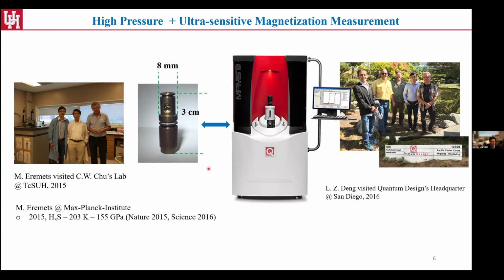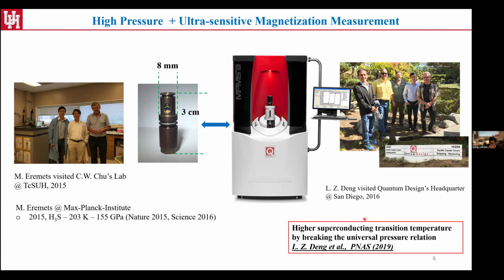With that experience, I got into doing magnetization measurements under high pressure. One of the key challenges is that, imagine putting everything into this SQUID, what we map out is not only the tiny sample, but really everything, including the background of this beryllium copper cell, the gasket, everything. That really requires a lot of careful background studies. For that reason, I visited QD headquarters, where they were very supportive, and I gained a lot of insight into the mechanism of this machine. That led to our later paper on breaking the universal pressure relation using this ultra-sensitive magnetization measurement technique under high pressure. It was a very interesting experience.